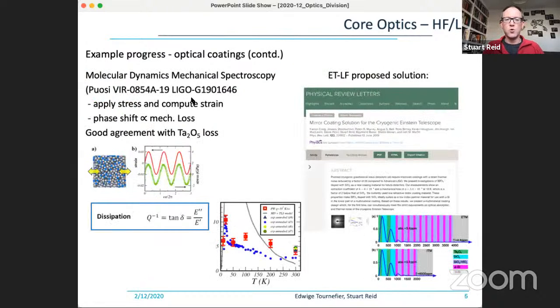There's lots of work being done in other groups in terms of atomic simulation studies. I'll just cite one by Puosi, looking at applying a stress within the atomic structure, computing a strain, and quantifying the phase shift. That's then found to be correlated to the measured mechanical losses. And there are some really nice results trying to tie in the low temperature dissipation peak in tantala coatings in relation to these simulations.